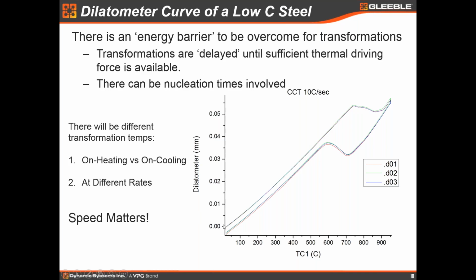So if I was doing a quasi-static experiment where I was heating very, very slow and cooling very, very slow, I would still not have much of a nucleation time because I'd be going slow, but I would have an energy barrier to overcome. I'd still need some superheat or some undercooling to get these transformations to proceed. And you see that in the austenite to ferrite transformations are offset, whether I'm doing an on-heating curve or an on-cooling curve.